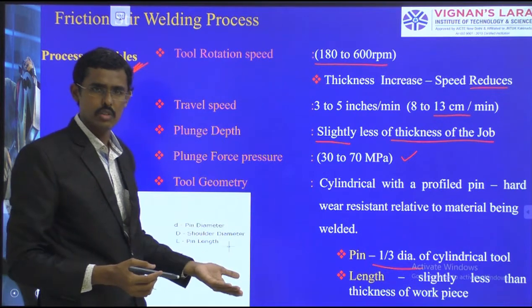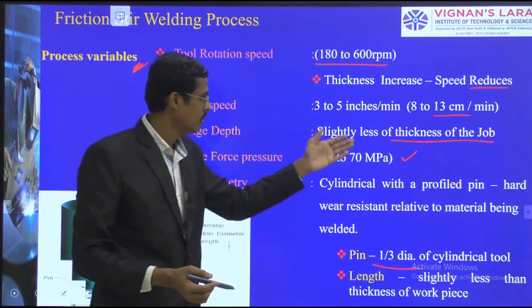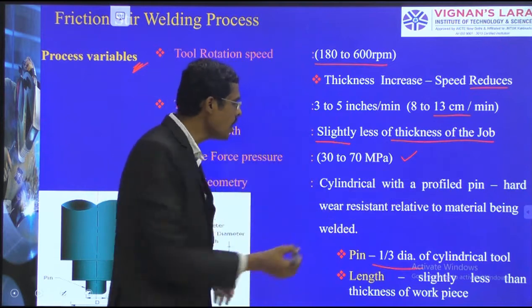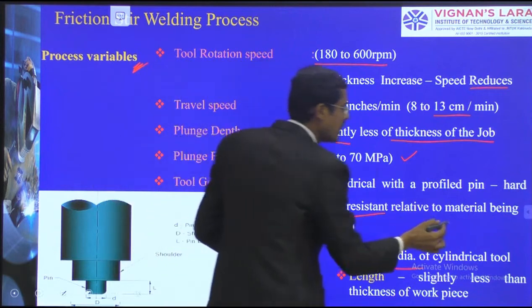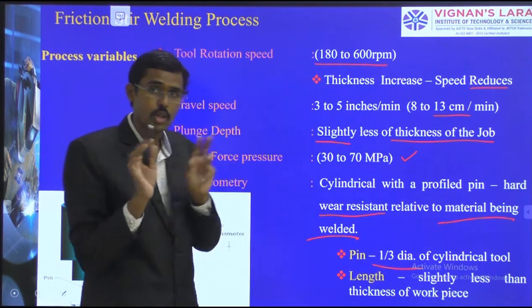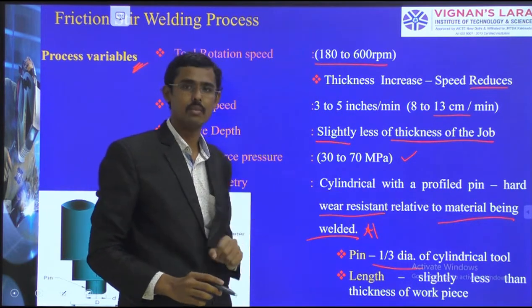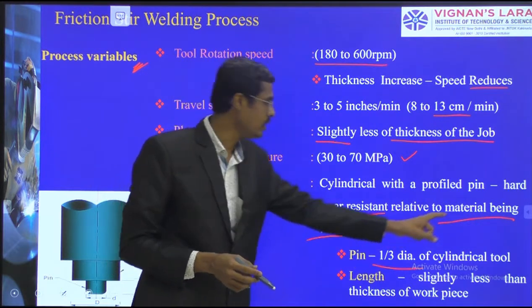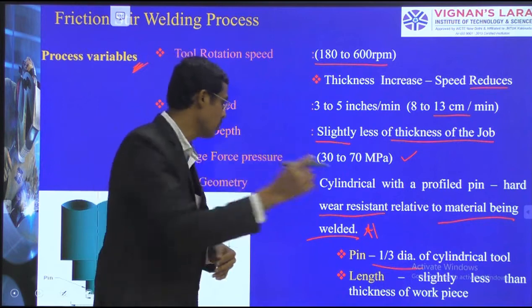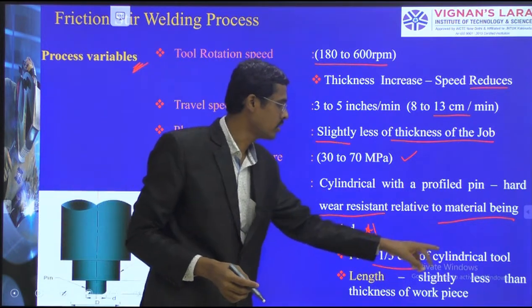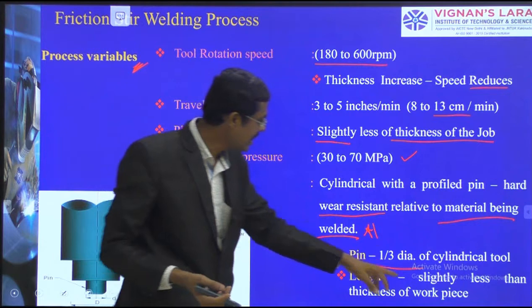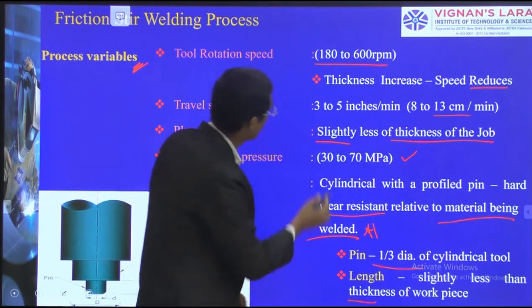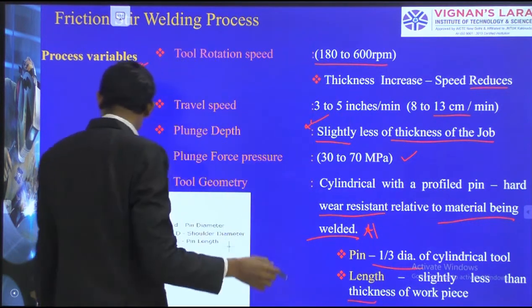Tool geometry, we know this. Maybe a cylindrical tool with a profile pin, with hard wear resistance. This we need, hard wear resistance relative to the material being welded. Which material are we going to weld? It is aluminum, so the tool has to be higher than that. The tool should contain higher wear resistance than that of the specimen which you are going to weld. So the pin is 1/3 of the diameter of the cylindrical tool and the length is slightly less than the thickness. This point we have discussed here. Okay. So this is what.